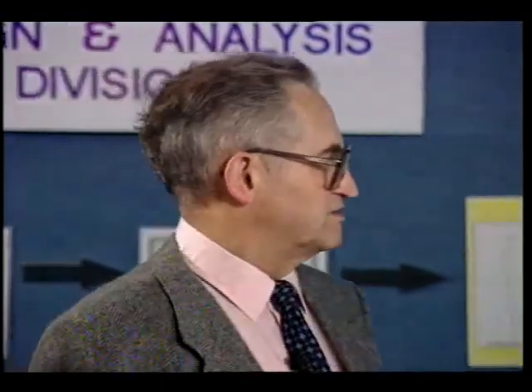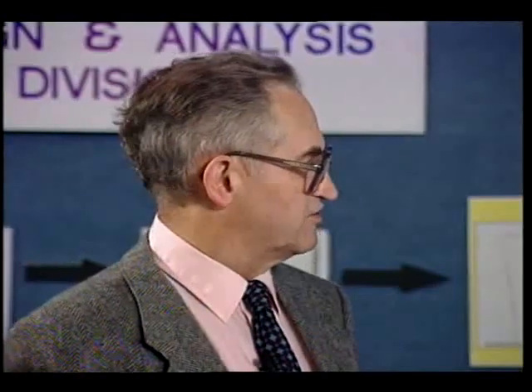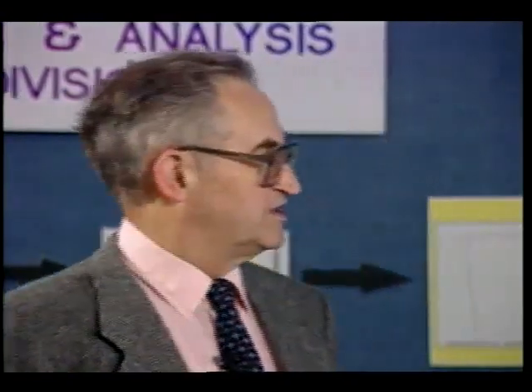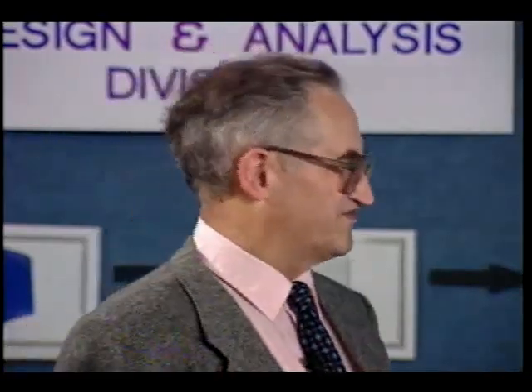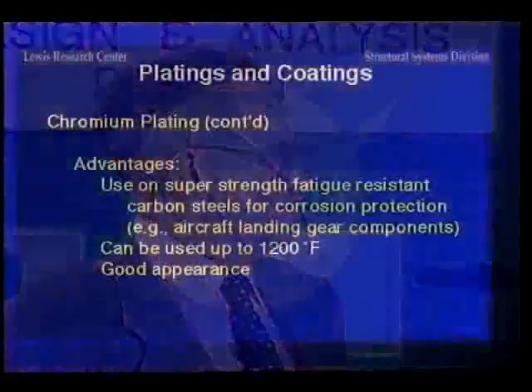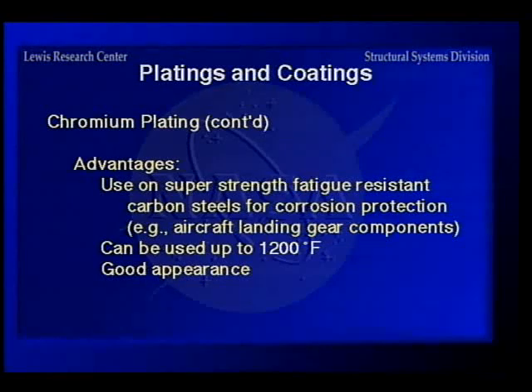But to get a good chrome plate, you've got to put a copper strike on first, and then a nickel over that, and then the chromium goes over the two of them. Otherwise, the chromium is porous to a certain extent. So unless you have something under it to help it, it doesn't work out too well, or you have to go with a fairly thick coat. And it can be used up to about 1200 degrees, and of course it looks good.